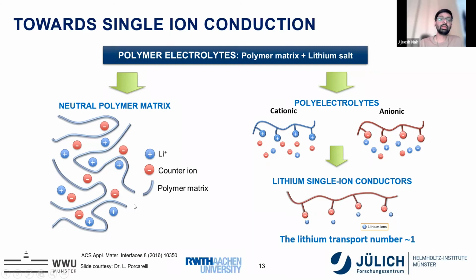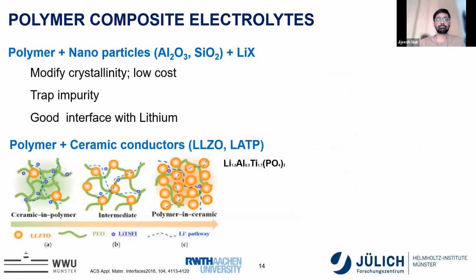Whereas in the case of PEO-LiTFSI, you have cation and anion, both mobile. So maybe only 20% of cation is mobile and 80% of anion is mobile. From that simple system, to only 100% lithium being mobile and anion immobile, is something where we can improve the overall ion dynamics within the polymer electrolyte system.